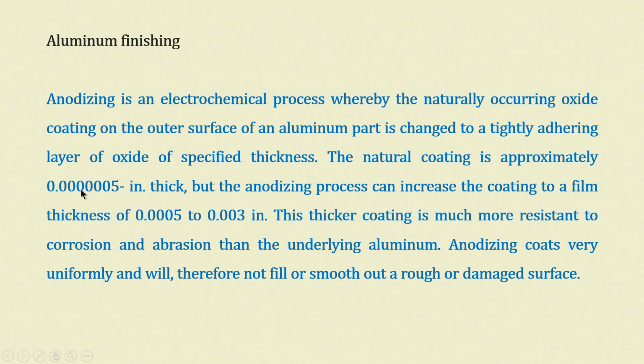This is the natural coating of aluminum, 0.0000005 inch thick, but the anodizing process can increase it to 0.0005 to 0.003 inches. So, from 0.0000005 to 0.003 is a very large increase in thickness. This thicker coating is much more resistant to corrosion, very simple to imagine, and also more resistant to abrasion than the underlying aluminum. That is why aluminum materials always need to be anodized or coated.